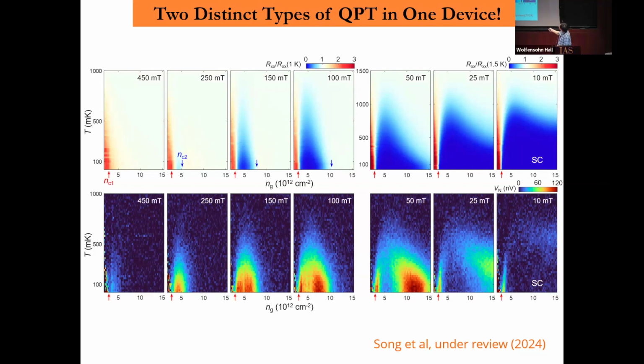You see this is very different behavior. As I said, there's a dome, but one side of the dome, the high density side, is very sensitive to magnetic field. Zero field like this, and small field goes this way. But the low density side of the dome has no dependence on magnetic field. Do you see this? This is very strange. The critical point is fixed here, it doesn't change.